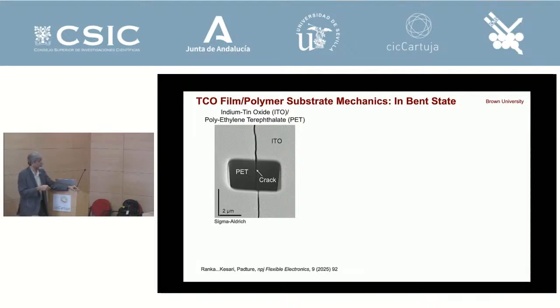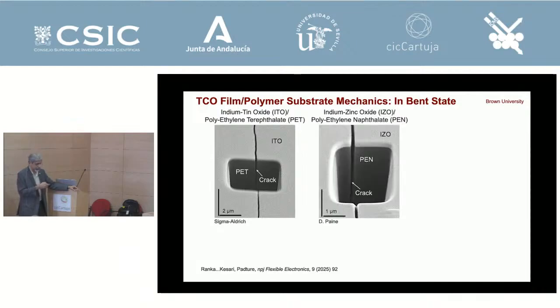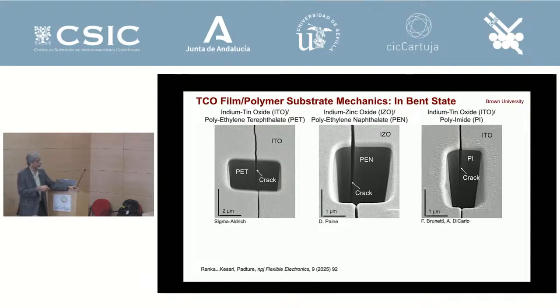This is ITO on polyethylene terephthalate. Then this is IZO, indium zinc oxide, on polyethylene naphthalate. And this is Kapton, polyimide, with indium tin oxide. All of them, some of them homemade, some of them purchased. So we thought that commercial materials, maybe they do weird things there. But this is a universal phenomenon, where this infinitely tough substrate under a film is cracking like a ceramic. And so that's a problem, because if the substrate is like the foundation of your house, if it's cracked, you need to worry about it, right?